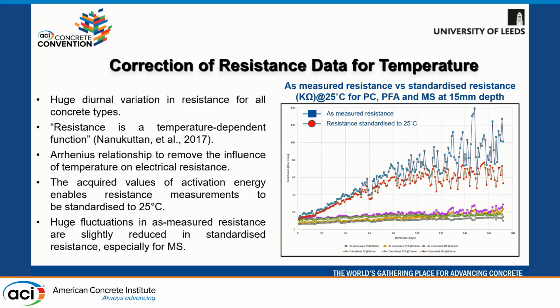So as we know, concrete is affected by temperature. If you see in the graph, the squared blocks represent as-measured resistance, and there is huge diurnal variation in resistance for all concrete types. This is because concrete was kept outside and it was subjected to temperature variations. So what we did was we applied the Arrhenius equation to remove the influence of temperature on electrical resistance. The acquired values of activation energy from the relationship enabled resistance measurements to be standardized to 25 degrees Celsius.